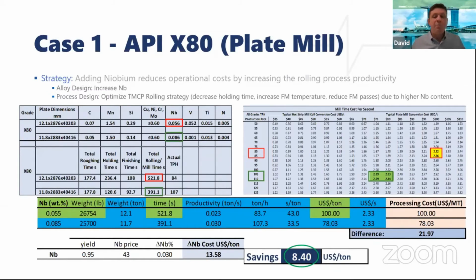That gave them $8.4 per ton total process cost reduction, already considering the higher niobium cost. I did not even put in this calculation the reduction of vanadium, okay? This is just niobium versus process. So it's 8.4. In actual cost, the overall cost, this product was even more interesting than 8.4.